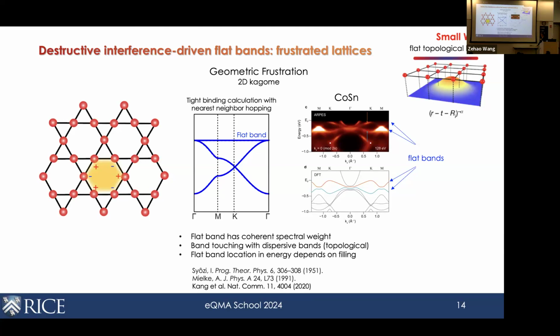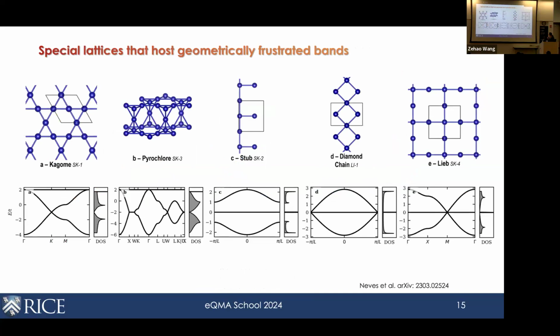So this is the work by the MIT group here. Then you may ask, how do we find systems that have this kind of destructive interference-induced flat bands? Of course, Kagome is not the only one, and there have been multiple efforts to search for similar kinds of lattices that can give you this kind of destructive interference. And this is one example, where they've gone through ICSD and identified the most commonly occurring lattice motifs that give you these flat bands. And these are the most common 5, right? With Kagome being the most common one, followed by pyrochlore and so on and so forth.